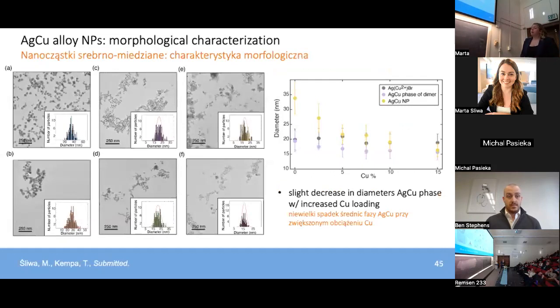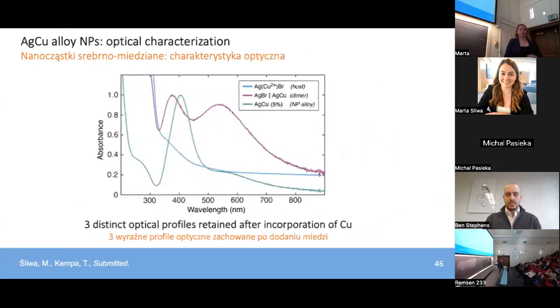So we characterized the products that we were able to yield from this reaction across that 0 to 15% copper range using TEM. And we saw that independent of the amount of copper that we introduced, here going from 0 to 15% copper nominal loading, we are able to yield spherical silver copper alloy nanoparticles. We do see a slight decrease in the diameter of those silver copper alloy nanoparticles when we increase to the higher limit of 15% copper. And this is likely due to some strain effects as we introduce more amounts of copper, which cause smaller and rounder silver copper nucleates to form on the surface of that host.